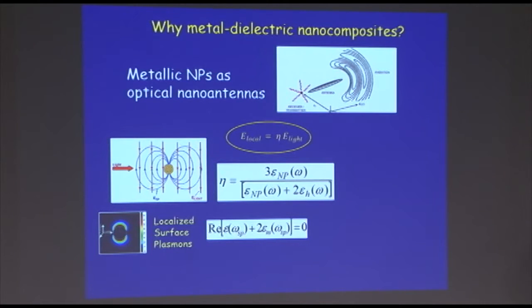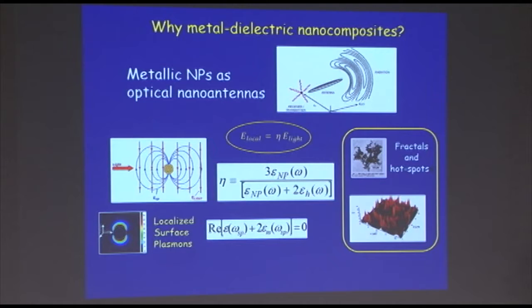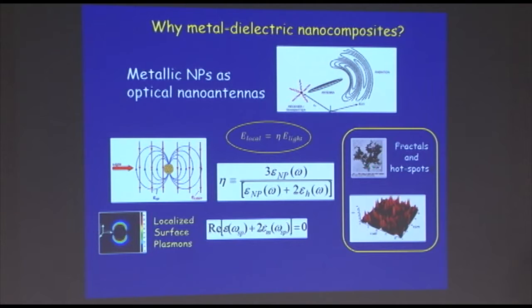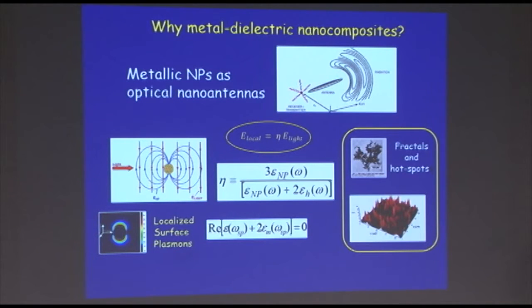What I'm going to show is a kind of plasmonics in disordered material. The field can be very large: for one metallic particle, if I get the denominator equal to zero, I can reach a local field factor of 10 to 100. But if I have agglomerates of particles, I have what are called hot spots — regions between particles where the electric field can be on the order of 10,000 times larger than the optical field. The intensity, which goes as the square of the field, can be enormously larger than the incident intensity, so you can do nonlinear optics even with low amplitude fields.